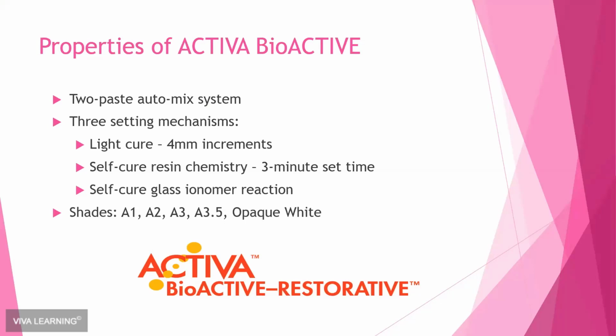The material can be light cured up to 4 millimeters, but it also self-cures. So there's a resin chemistry that happens over a 3-minute set time, and then there's also a glass ionomer reaction that's occurring. So you have the option to cure this material or to wait for it to set, maybe a combination of both. And I would say frequently I'm doing a combination of both. And then again, it comes in the A shades and then opaque white, which is marketed as the kids version, but it's basically just the same material in a bright white.